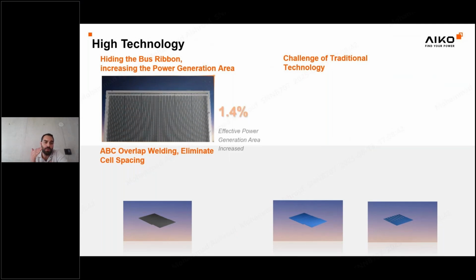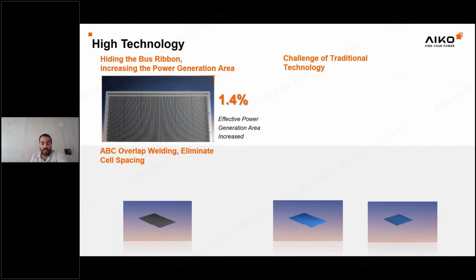Normally, you have them at the top of the panel, in the middle, and at the bottom edge. So we managed to fold them on the backside, and this kind of folding process helped us to increase the effective power generation area by 1.4 percentage.